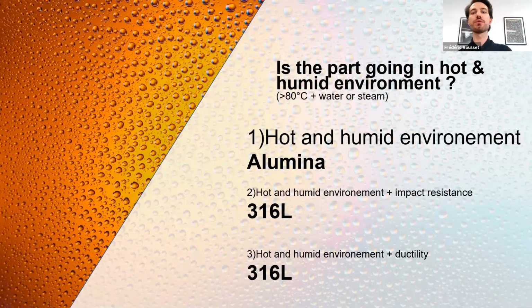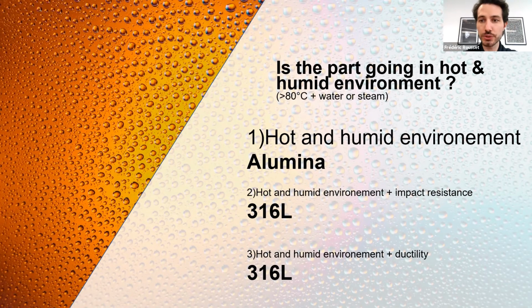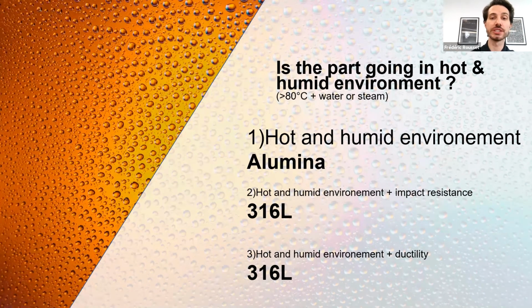If you have an environment that is quite hot and humid, so over 80 degrees with water or some steam, you use the alumina first, the best material that we have. You can use the 316L for the fact that it has an impact resistance and some ductility, and it can resist hot and humid environments.